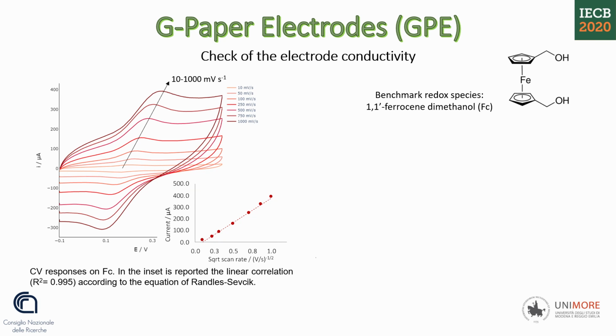Preliminary tests with ferrocene dimethanol demonstrated that our electrodes possess a great conductivity and they respect the Randles-Sevcik equation, as demonstrated by cyclic voltammetries taken at increasing scan rates. This also demonstrates that there is a diffusive charge transport mechanism from the solution to the electrode.